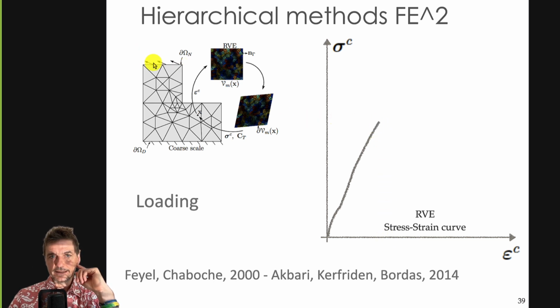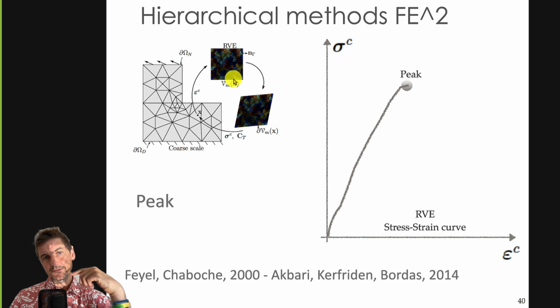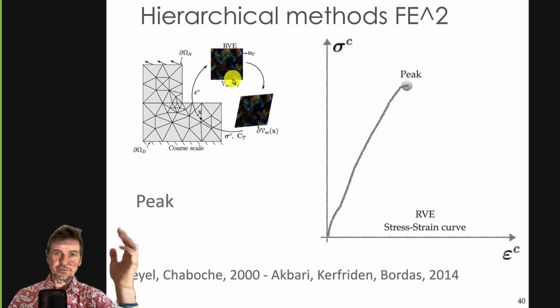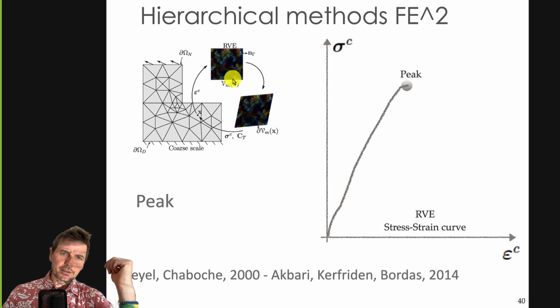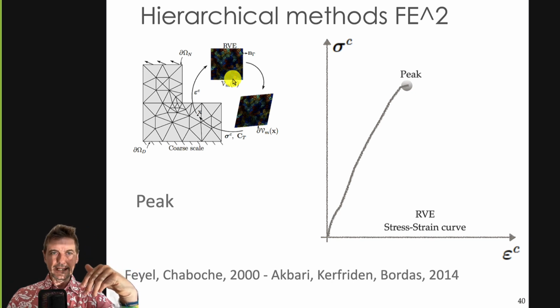So we keep increasing the loading on that edge, which increases the displacement on these three nodes. And we keep loading, and at some point we reach a peak, which means the highest stress that particular point can see. That is due to the fact that in these RVEs, you may have fractures, you may have damage, you may have all sorts of problems taking place. You may have irradiation and some dislocations forming, or some atoms missing, or some atoms actually being completely thrown out of the lattice. And so you end up at a peak.